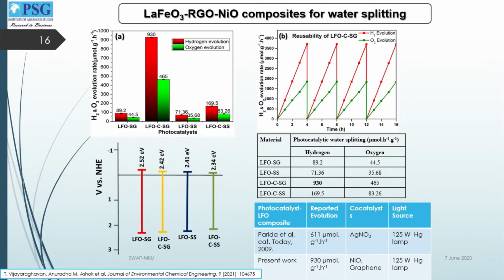Now we tried to use some inexpensive catalyst and also a graphene material and make them as composites. So we combined lanthanum ferrite with RGO, reduced graphene oxide, and nickel oxide, and we studied the water splitting capability. We found that this composite, sol-gel synthesized lanthanum ferrite with graphene and nickel oxide, showed one of the highest water splitting capability.